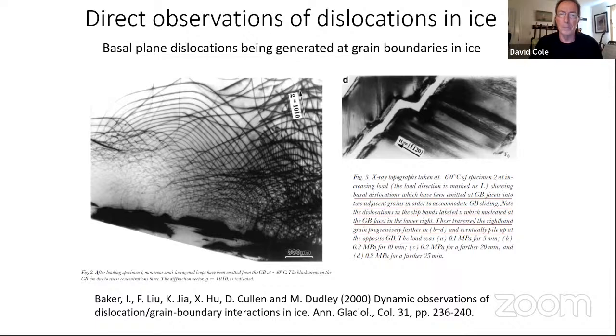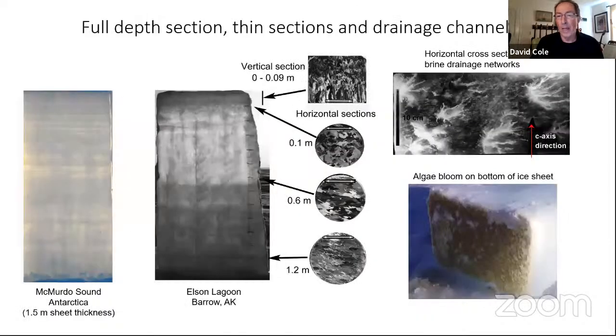And so what I'll be talking about is how I quantify and model the dislocations in ice and answer the questions that I posed initially, which is what's going on in these ramp loading experiments. So I always like to show a slide like this just to get us all thinking about our material. In our field work through the years, we've come up with a method to cut and remove these full thickness slabs that give a very nice view of the overall floe structure.